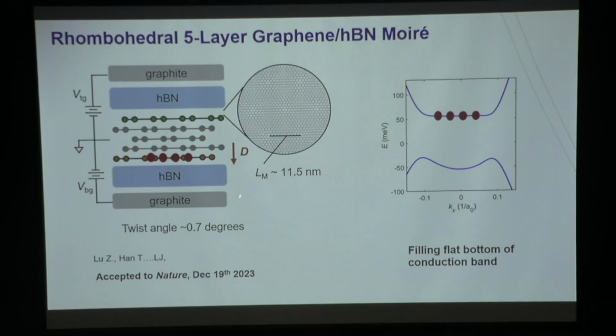Okay? And we applied a displacement field, we open up the band gap, and we put charges at the bottom of this conduction band where the dispersion is really, really flat. Spatially, these charges are located at this layer here, which is the upside of the Moiré. The Moiré is here, while the electrons are 5 layers away from it. I'll get back to that later.